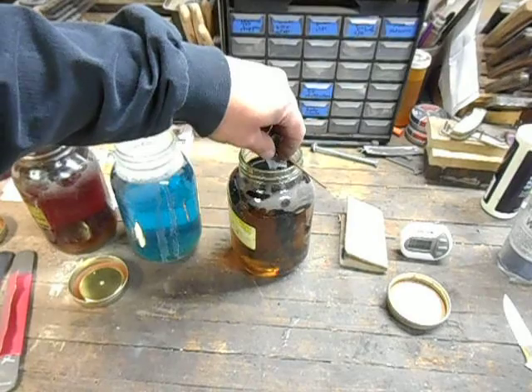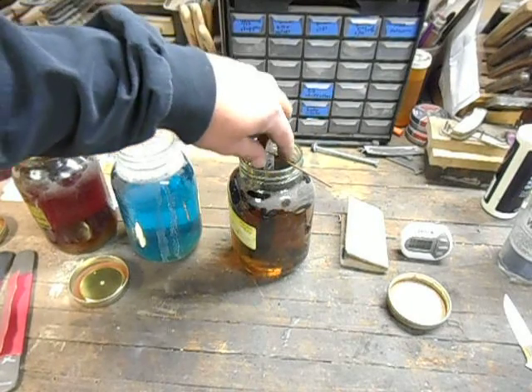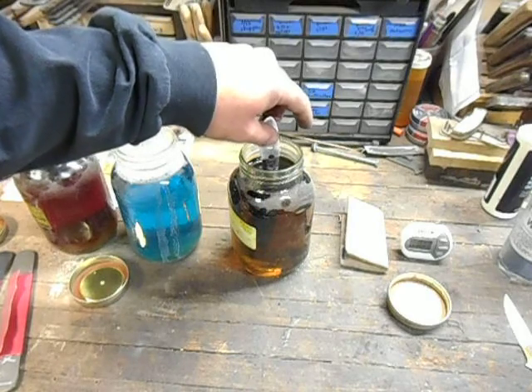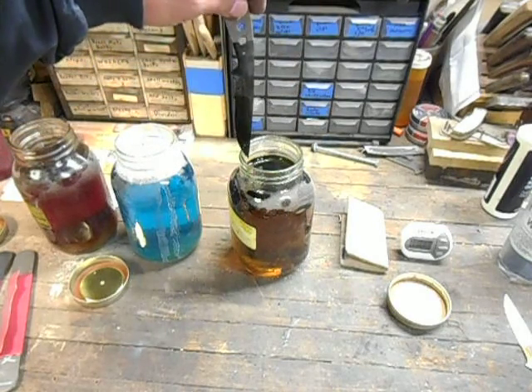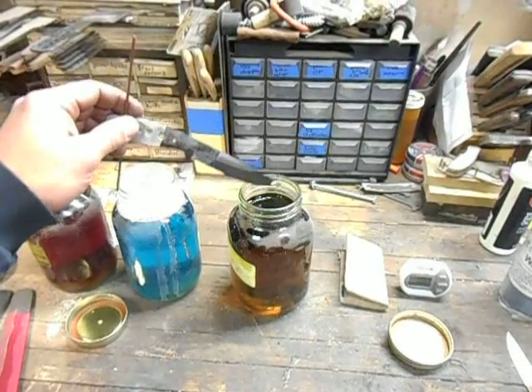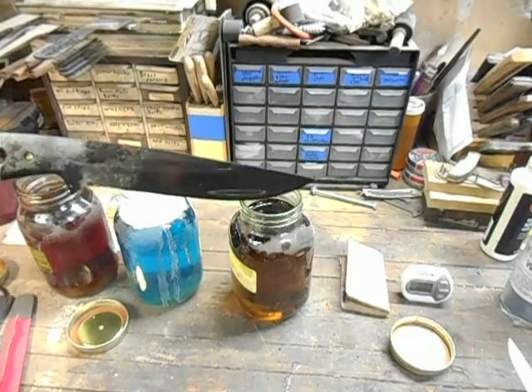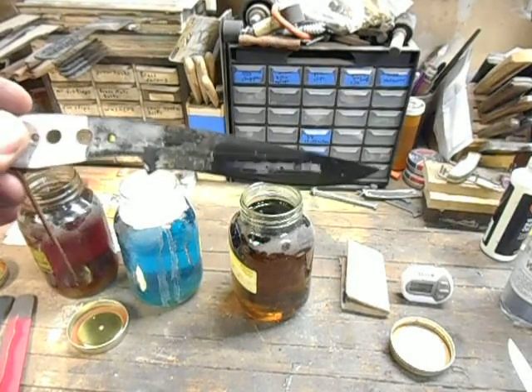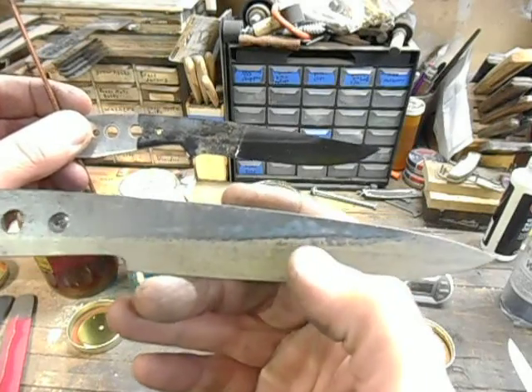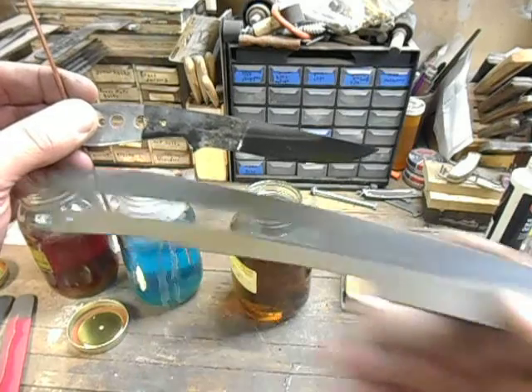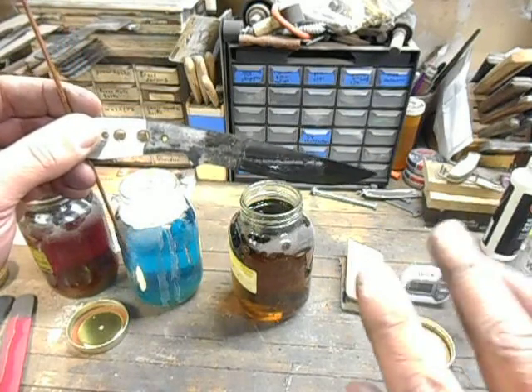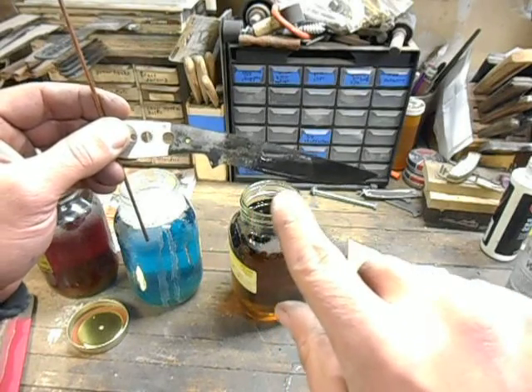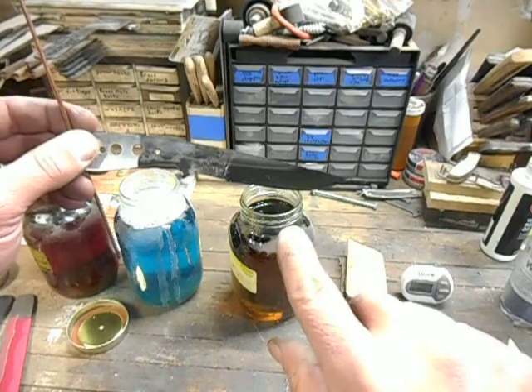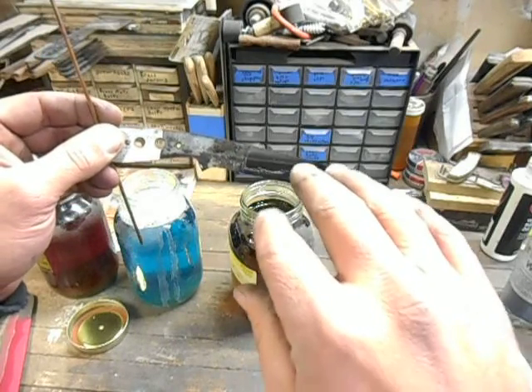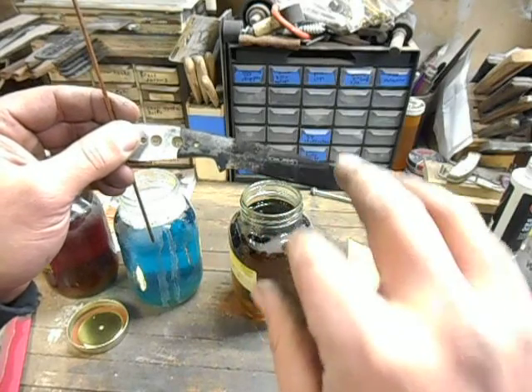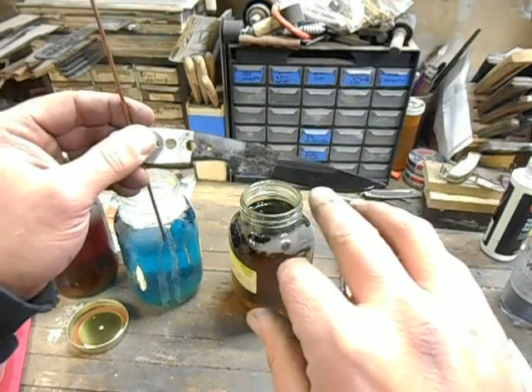So anyway, here's the blade. I've got just a rod sitting through one of the tang holes to keep it at the right level inside the ferric. And you pull it out. See that nice line right there? That is the same line that you would have seen before I ground it of the scale patterns. So we use the acid to etch the blade, and what it really did was the acid cut the hard part and the soft part differently, and that's where you get that variation going on there.